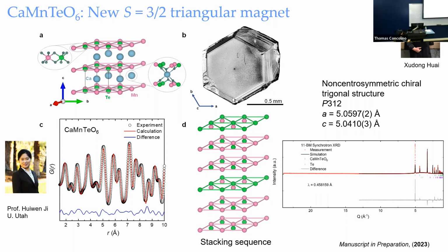My student grew these materials by mixing starting materials including calcium carbonate, Mn, I believe chloride, and then tellurium oxide. The tellurium oxide acts as both starting material and flux. He brought it up to a temperature of about 750 degrees C, followed by slow cooling to 400 degrees C, and then quenched it. That's how we got this hexagonal phase.